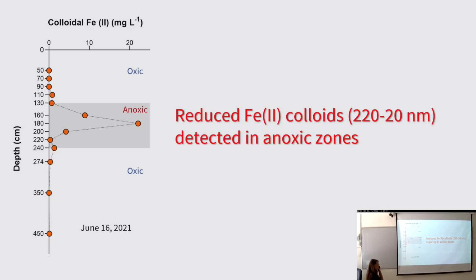In the spring months of May and June, we detected high concentrations of reduced iron-rich colloids. Here I'm showing the concentration of colloidal ferrous iron as a function of depth. You can see really high levels that were detected in the anoxic zones. We define colloids to be in the 20 to 220 nanometer size range.